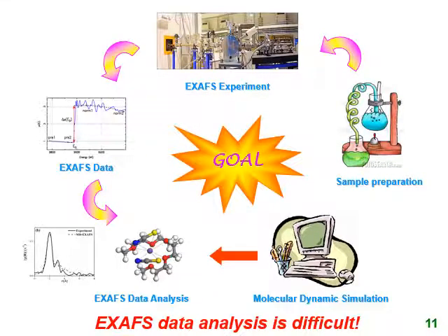So as you can see from the previous slide, fitting the data with many parameters is a very difficult task. Normally people start with sample preparation, then go to the synchrotron to do EXAFS measurement. After that, they go home and try to do data analysis by the fitting procedure. The most difficult problem is obtaining a model to explain the experimental data, as most of the samples using EXAFS are amorphous or non-crystalline materials. In most cases, people use a model crystal which has the closest structure to their system as the fitting model.